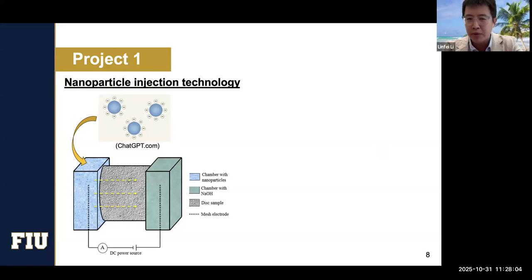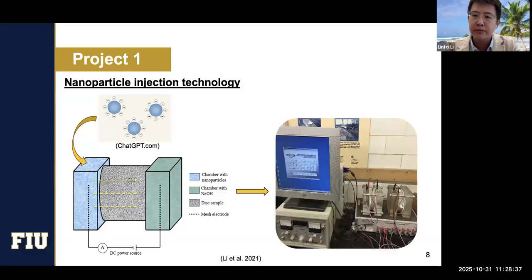Some of you may be very familiar with this testing setup. It's basically the ASTM standard rapid chloride penetration testing system, but we made some modifications to it. On one side, we did not use the sodium chloride solution, but instead we use a nanoparticle solution. Because of the surface charge, you can generate electron migration, and use the electrical driving force to push the nanomaterials into your cement, which can help to densify the microstructure, but more importantly, to seal the cracks. So this is basically the idea, with exactly the same setup as the RCPT test.